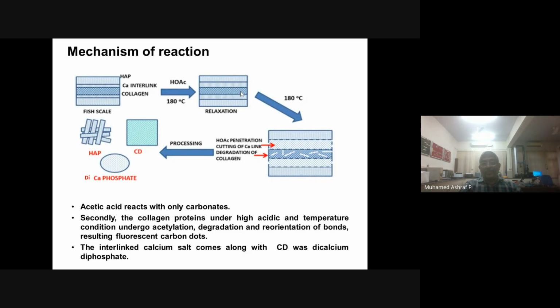And then what is the mechanism of this? When we take fish scale and add acetic acid solution, what is happening? When we heat it at 180 degrees centigrade, the fish scale undergoes a little bit of expansion or relaxation. Then immediately the acetic acid will attack the calcium, penetrate and cut the calcium link between the collagen and the hydroxyapatite. That will change the orientation of all structures, and then it will become degraded, and the hydroxyapatite will go away. This collagen is converted to carbon dot, and the calcium used for the interlinkage between the hydroxyapatite and collagen will be separated out. So we could extract three systems. That is the basic reaction undergoing in this process.